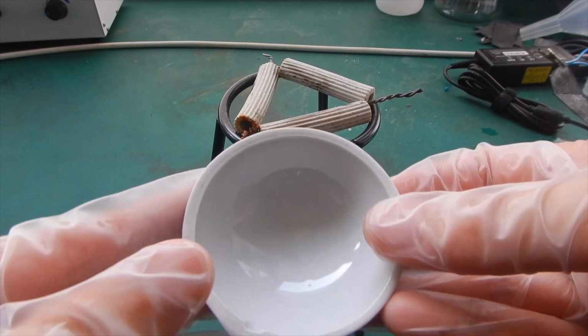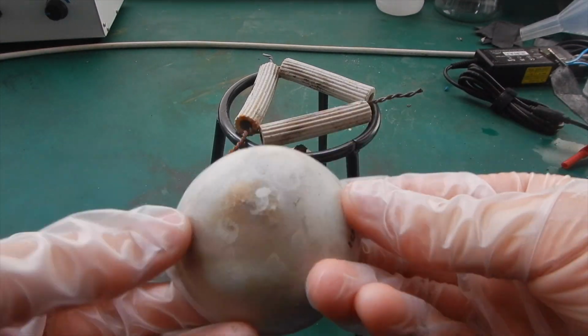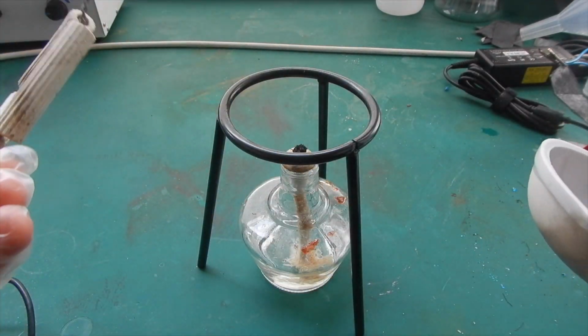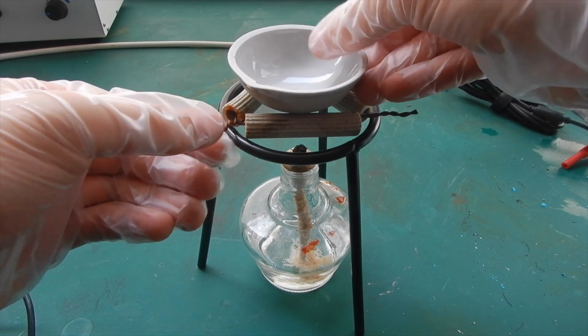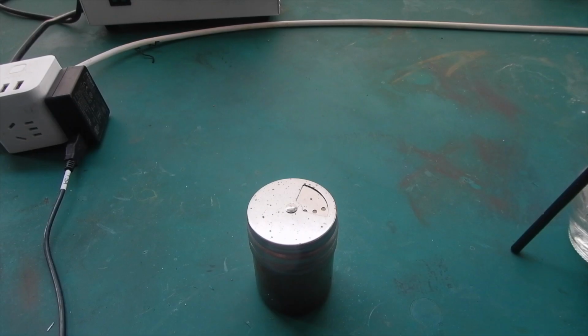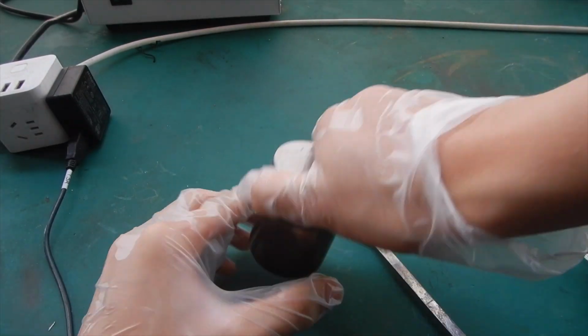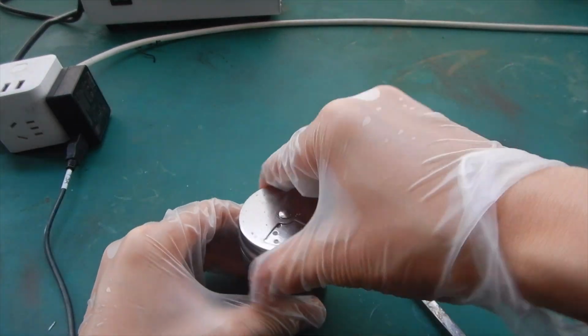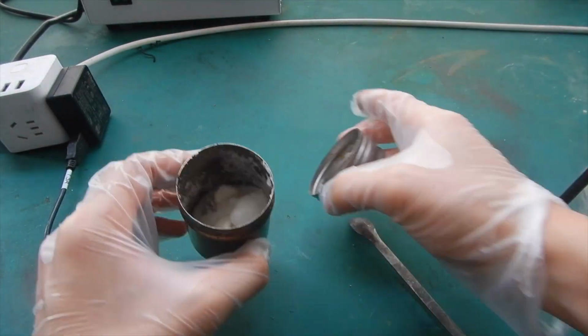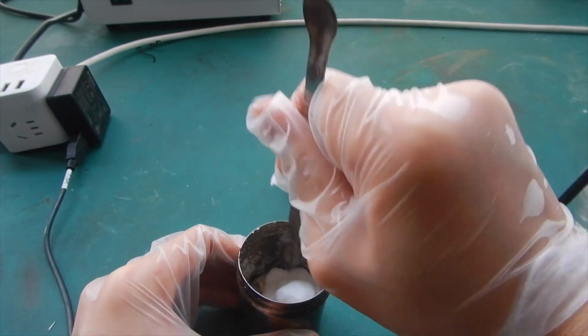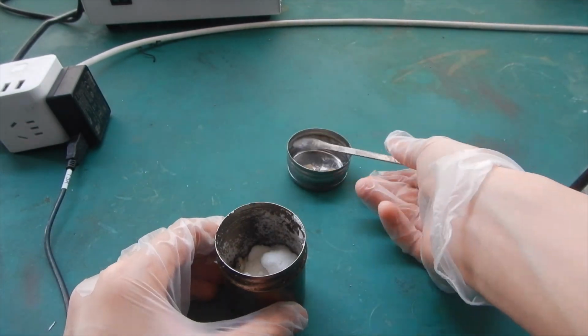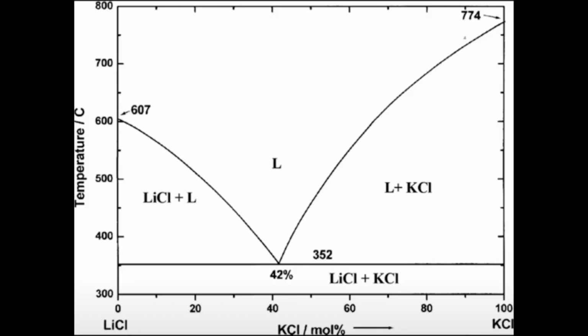I decided to do the electrolysis in a porcelain evaporating dish. It was placed on a tripod, and I preheated the dish using my alcohol lamp. Then I opened my can of lithium chloride potassium chloride mix that I salvaged from the school. Using a spatula, I mixed the salts well. The proportion of the salts by weight is 61% potassium chloride to 39% lithium chloride, which would give a eutectic mixture that melts at 353 degrees Celsius.